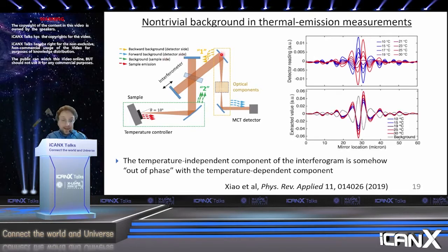In particular, because we have one contribution that's not changing with temperature, and another contribution, the thermal radiation from the sample, that is changing with sample temperature, we can actually back out the component that's changing with temperature from the component that's not, and that's what we did over here. What we found is that the background turned out to be out of phase in the interferogram. This is not the phase of light, it's the interferogram phase, with the thermal radiation coming from the sample. By extracting the thermal radiation just from the sample, all of a sudden we were able to recover the expected behavior, which is the colder the object is, the less thermal radiation it gives off. So it was this complicated interplay between the backward thermal radiation and the forward thermal radiation that was giving us this counterintuitive and just wrong behavior where the thermal radiation was not monotonic with the temperature.